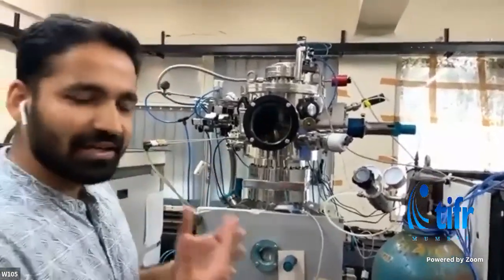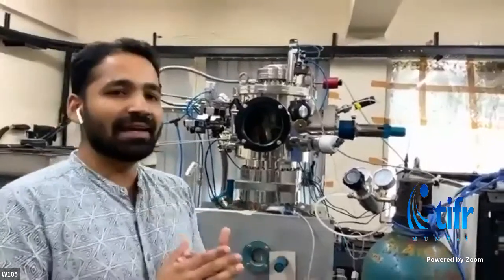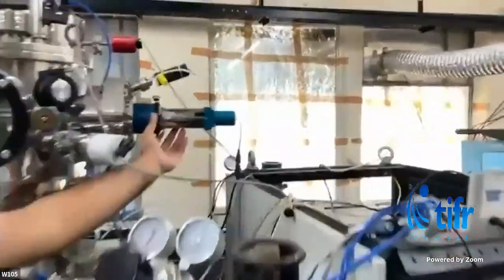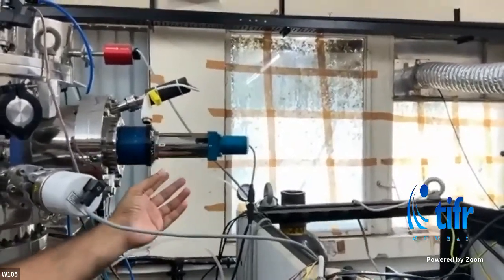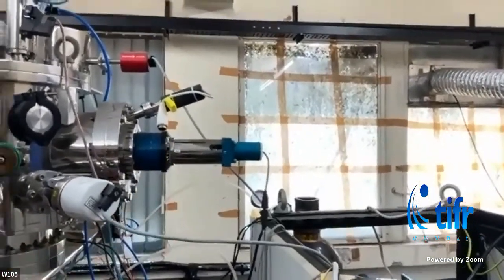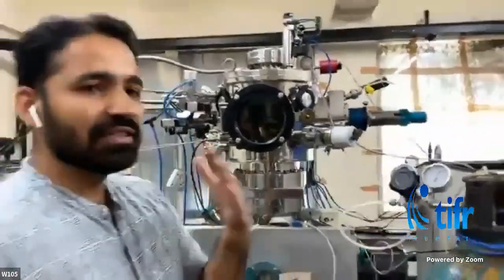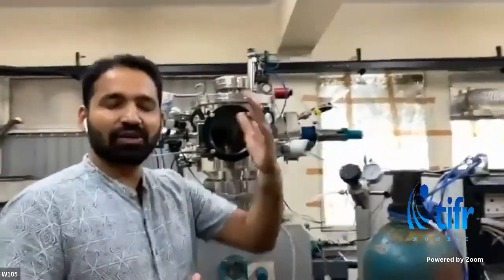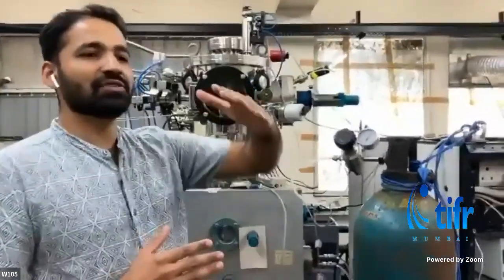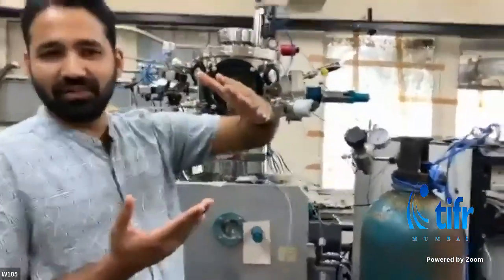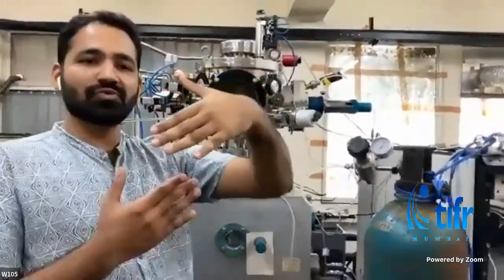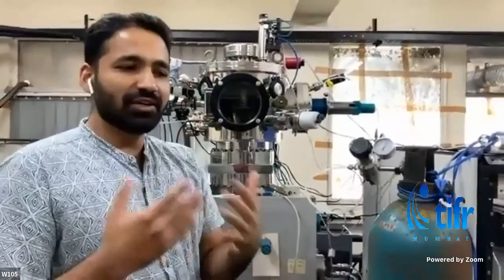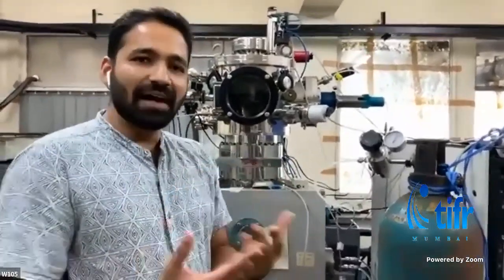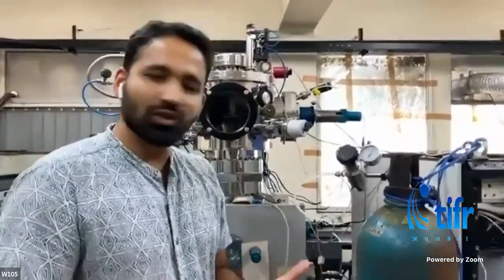Once we have this highly directional evaporation, we do a double angle evaporation. This is the control we have for setting the angle at which we want to evaporate. We basically rotate the sample head, and that fixes the angle. Then we evaporate at, for example, plus 20 degrees. Then we do oxidation in between. And then we evaporate at minus 20 degrees. So these two evaporations separated by oxidation form a Josephson junction.